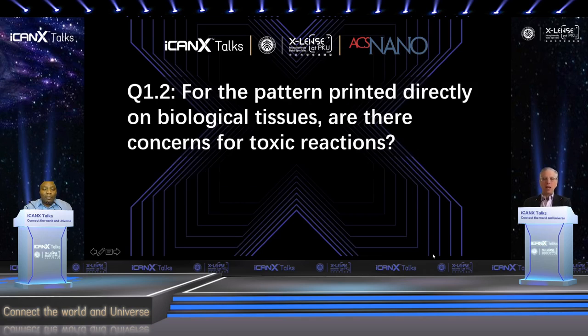Yeah, very good. Second question. For the pattern printed directly on biological tissues, are there toxicological concerns, or do you see reactions on the tissue or biological materials? Very good question. So there are different alloys that we have used on that. One of them, the bismuth metal, is very benign. Gallium, also very benign. But once you start going into the silver containing, the copper containing, then you start seeing biological effects. In fact, there are some alloys I didn't get to talk about that contain copper where we have seen the adducts that come out of there start repelling bacteria. So they're actually cleaning the space. But I do anticipate that if you have a hypoxia condition, you can etch out the metal ions, and that could have issues with the person or with the performance of the organ.